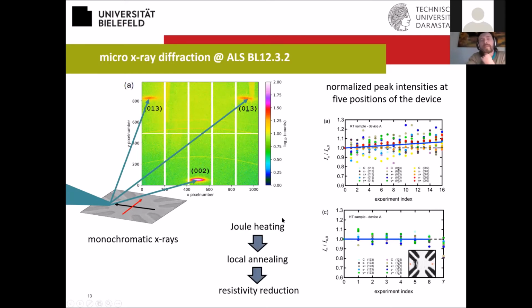We can summarize this basically by saying, okay, we have this Joule heating coming from the current density, which is pretty large. This leads to a local annealing in these narrows of the structure, and this can lead to a reduction of the resistivity due to crystal growth. The high temperature sample doesn't do that because it is already nice and epitaxial, so there is nothing to crystallize, in contrast to our room temperature grown polycrystalline sample.